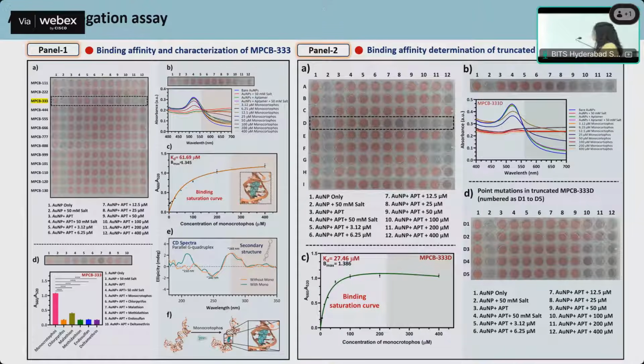To enhance its affinity, we did some truncation of the aptamer sequence and made several truncated sequences from A to I, where we found that aptamer MPCB333D was giving good results. This is the UV spectra of the same at different concentrations of monocrotophos. This is the KD value, which gave us very good results. It dropped from 61 to 27 micromolar.